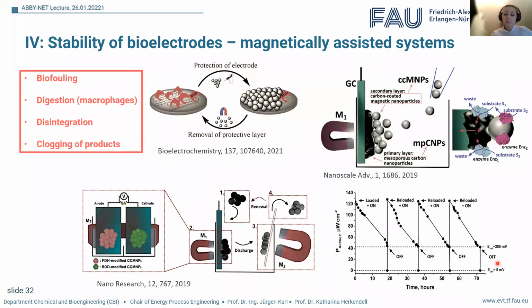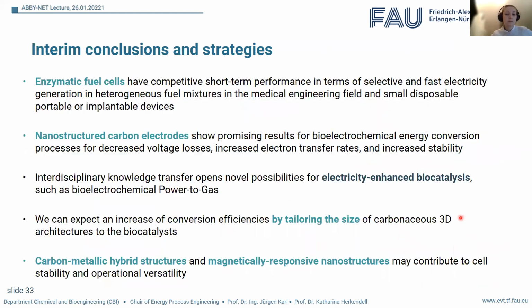And we developed a kind of bypass mechanism with a biofuel cell completely being able to react to deteriorating performance of the biocatalysts by using them on magnetic nanoparticles and being able to recharge the systems by replacing the biocatalyst even under operation, which you can see here in a long record of the power output of this biofuel cell based on fructose dehydrogenase and bilirubin oxidase, which could always be completely re-energized when it dropped under a cutoff voltage of 40 microwatts per square centimeter.